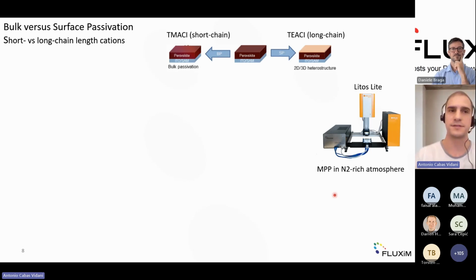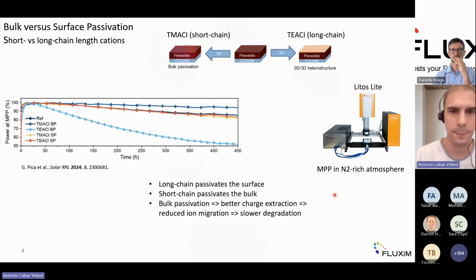Here we have a study on passivation. And the idea is to compare the impact of bulk and surface passivation on stability. In this very specific case, I will not specify what kind of passivant is used. It's just they compared the chain length of cations and tested the stability in order to see their impact on stability itself. So what they observed was that if you have a long chain cation, then you're passivating the surface. If you have a short chain cation, then you passivate the bulk, and this helps in slowing degradation.